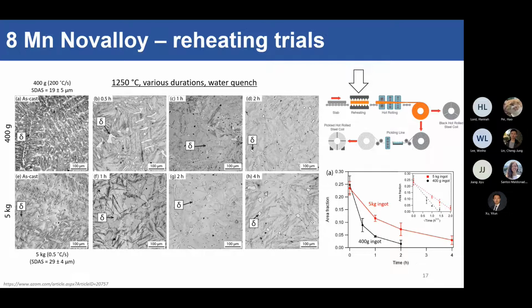If we plot the area fraction of delta ferrite with time, you can see that we've got this inverse square root graph here. And that's not very good news. That means that the last bits of delta ferrite run out here. It's very, very hard to get rid of. But anyway, you only have 2 hours to reheat your steel, so we are stuck with this microstructure. We have a little bit of delta ferrite left. Okay, we'll live with that.